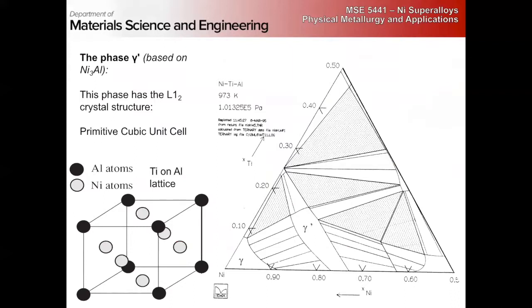And you'll see it looks like an FCC unit cell, except we have aluminum on the corner and nickel on the face. But remember, if these were random, it would be FCC. But since it's ordered, it is actually a primitive cubic unit cell. This is a question I like to ask in candidacy exams, especially for metal people. You'd be surprised the number of people that get it wrong when I ask, what's the crystal structure for the L12? It's particularly embarrassing for one of Professor Mills' students to get this wrong.